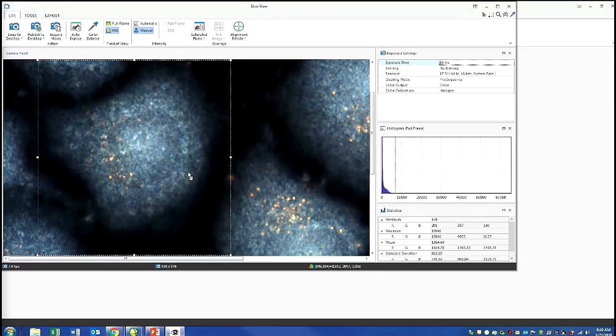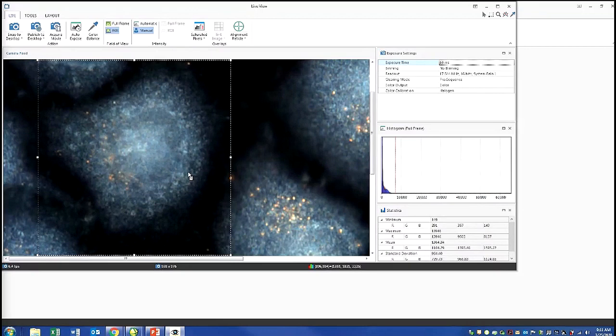So we're going to zoom in on that cell and take a real quick look at that. Okay. And so we're at 100x and we're zoomed in significantly here. What I really want to show you is that as we focus in and out of the Z focal plane, you can see nanoparticles come in and out of focus, which is a really significant indicator that these nanoparticles are not just on the cell structure, but we actually have internalization of some of these nanoparticles in the cell itself, okay?